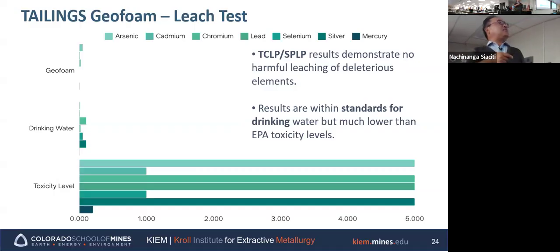TCLP is the toxicity characteristic leaching procedure, and SPLP is the synthetic precipitation leaching procedure. These are EPA standard procedures to measure how much heavy metal comes out when the material is exposed to water in another environment. As you can see, this is the toxicity level of the tailings, this is the drinking water regulation by the EPA, and this is the geofoam that we fabricated. So this is much less than even the drinking water standard. That's one of the bigger advantages, because we made tailings of the tailings to get rid of heavy metals.